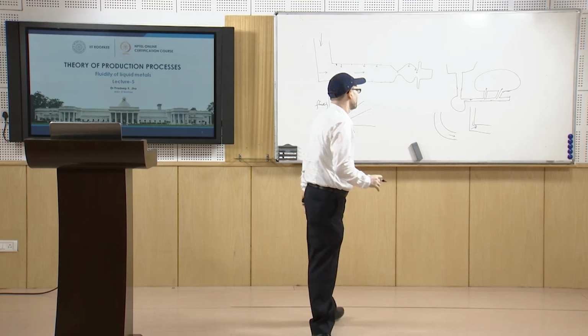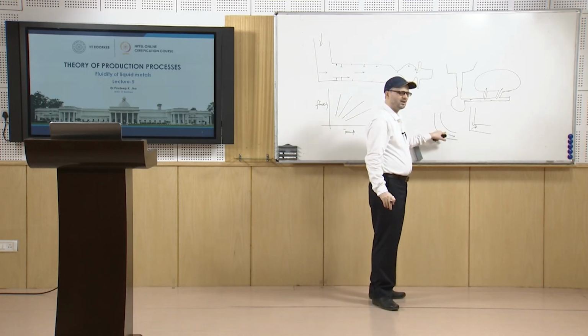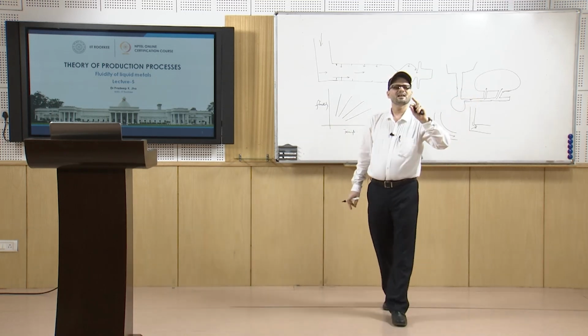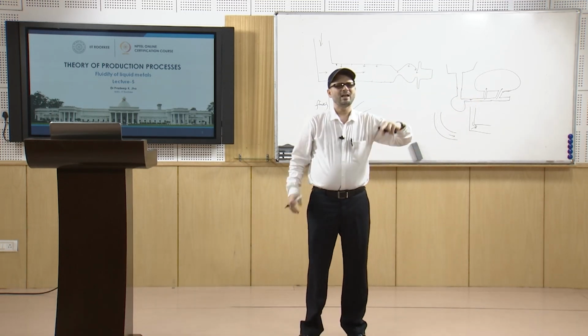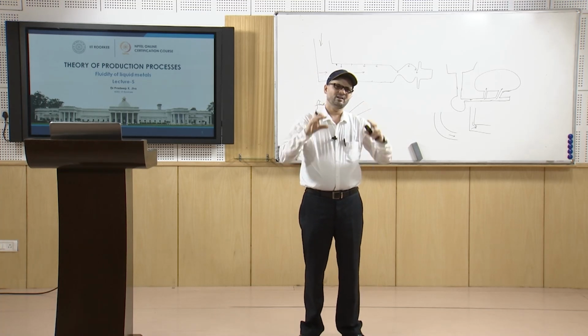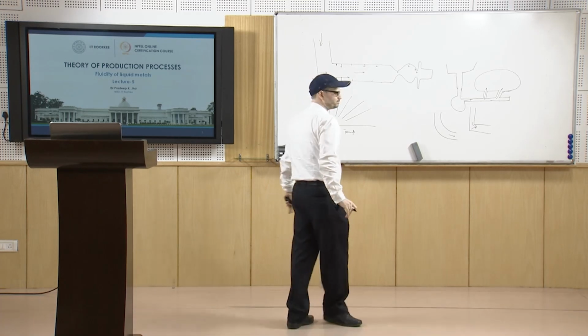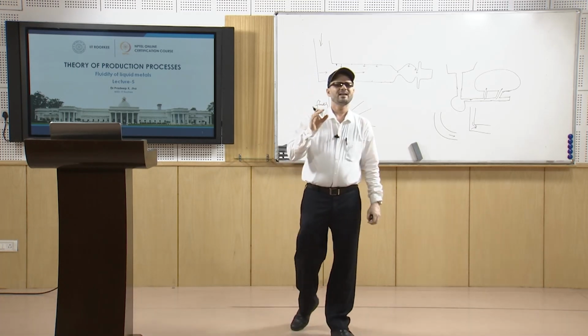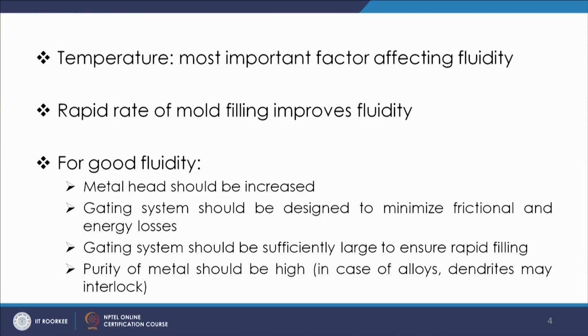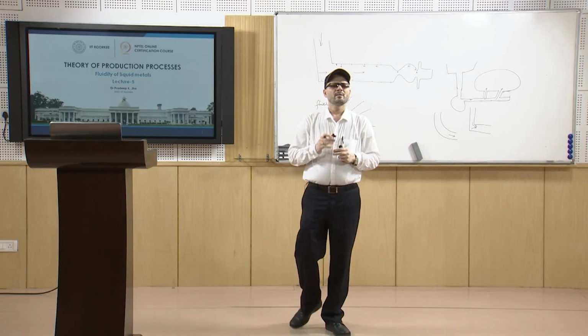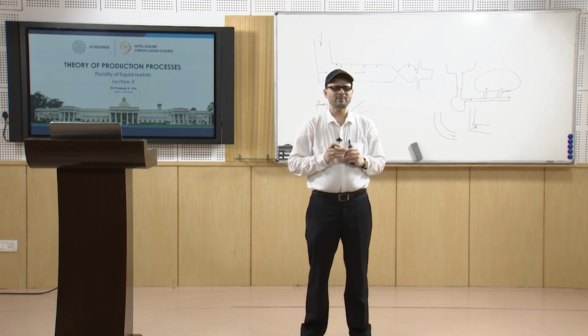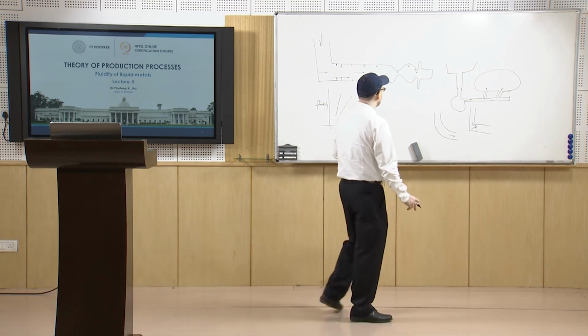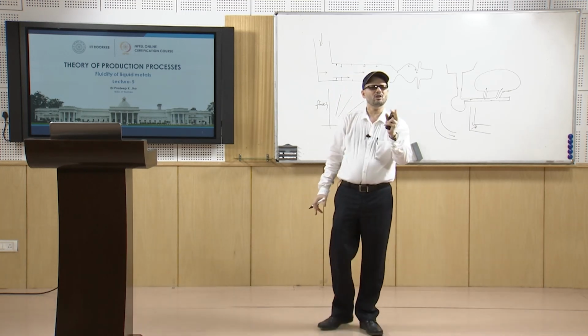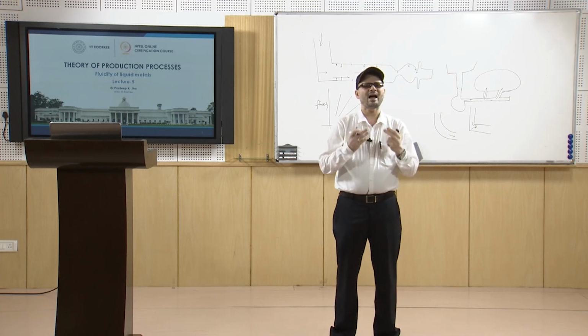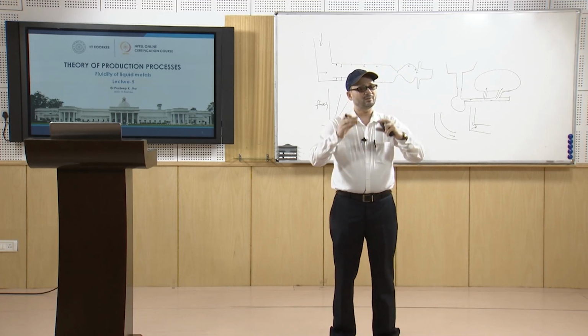That will basically reduce the energy losses. Once the energy lost is less, once the frictional amount is less, the fluidity can be maintained at a higher value, and you can ensure that in certain time the liquid metal will fill the cavity. Second point is that the gating system should be sufficiently large to ensure rapid filling. So, you must have sufficient large capacity so that you ensure the rapid filling. Purity of metal should be high. What happens is that you may have metals, in one case it is pure, in another case it is not pure. If the purity is not high, the fluidity is also affected.